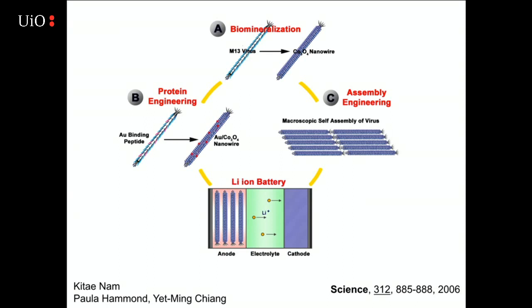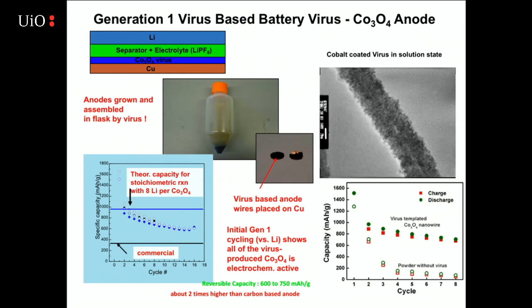And so then we wanted to actually have it assemble into a battery. And so this is all done in a shaker using kind of traditional biological tools. In this case, it's a single virus-based nanowire with very small crystalline cobalt oxide that's all nucleated on top of it. We used that material on copper with a separator and electrolyte, and lithium as a counter electrode.